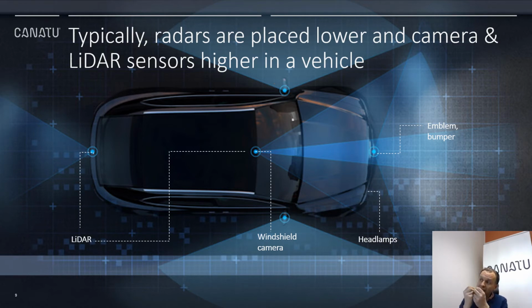Our material transmittance in the visual wavelength range as well as at typical LiDAR wavelengths is super high. So it doesn't matter whether we are talking about the roughly 900 nanometer LiDARs or those 1550 nanometer LiDARs, our transmittance is super high while maintaining high conductivity. In the radar area, our benefits are not so obvious, but we are operating there as well. But the typical application our customers are interested in is really camera and LiDAR de-icing.